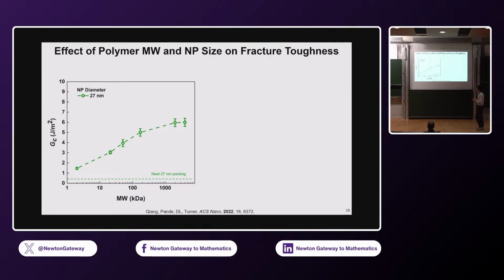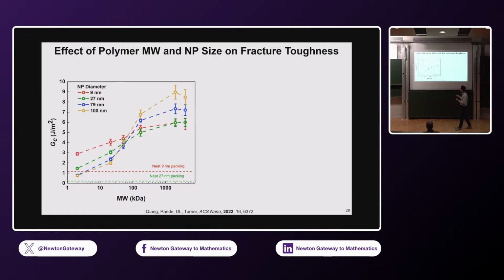Okay, so we have polystyrene, and its molecular weight increases as you go from left to right. This is the fracture toughness. And as you can expect, for a given nanoparticle size, as you increase the molecular weight, the toughness goes up. So that's not that surprising, right? And that is true for all different types of nanoparticles, okay? As you increase the molecular weight, the toughness goes up in general.